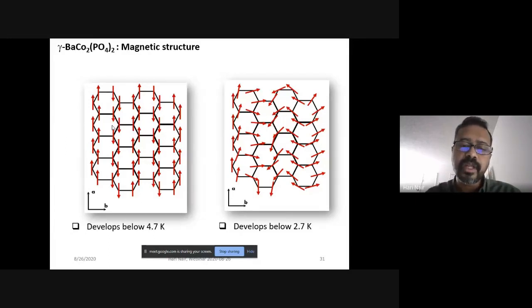And then you further cool down the sample, and in some other region of the sample, you would have this type of ordering, which is completely non-collinear. So it's not in a random order, but it is helical. So in some direction, it would look like a helix. And that develops only below 2.7 Kelvin.